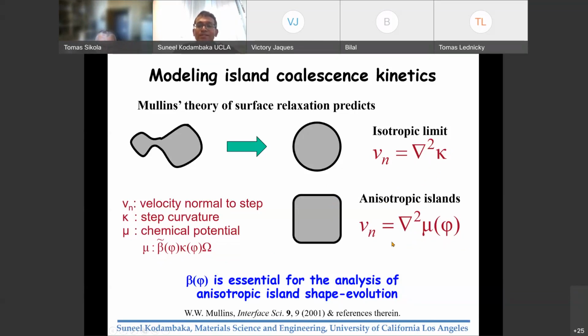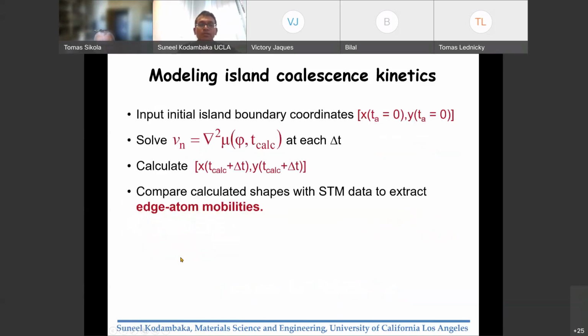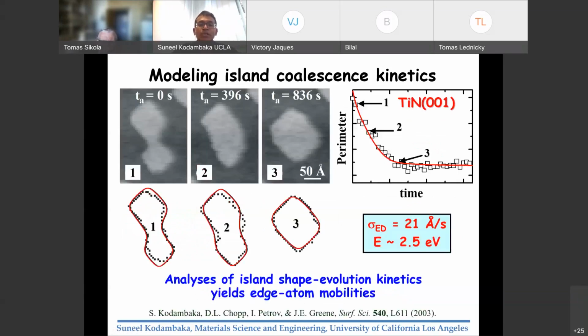And there is no analytical solution for this because now you have strong variations in both these parameters as a function of orientation. So this has to be modeled. But once you model it, you can extract quantitative parameters, such as the activation energy associated with edge diffusion. The reason is that when the islands coalesce, this is a far from equilibrium shape. The surface energy for this island is high, and so eventually it relaxes to this equilibrium shape.